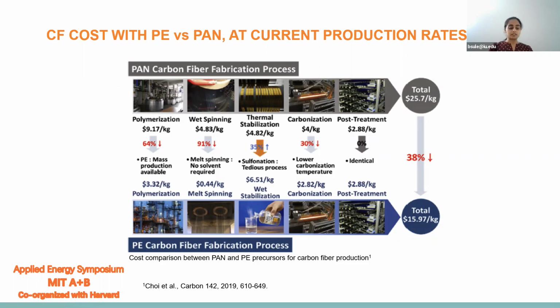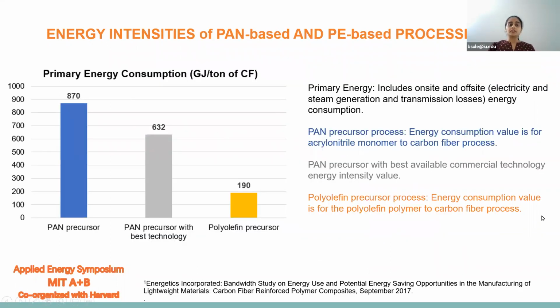However, overall, the cost in the PE-based fabrication process is significantly lower as compared to the PAN-based process. By using polyethylene as a precursor, the carbon fiber cost can be brought down to about $16 per kg from around $26 per kg. And also, if this polyethylene carbon fiber production is scaled up, as for automotive applications, then this cost can be further reduced. So here you can see the energy intensity of PAN-based and PE-based processes.